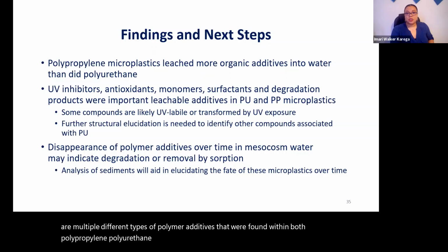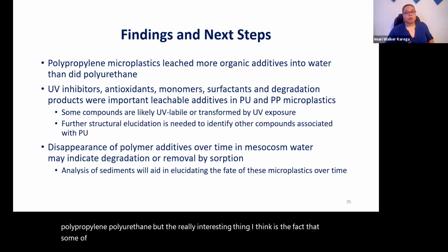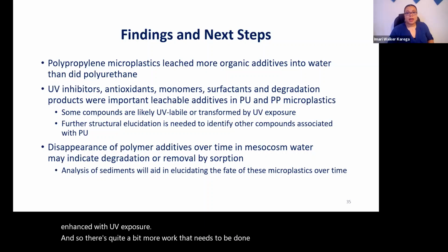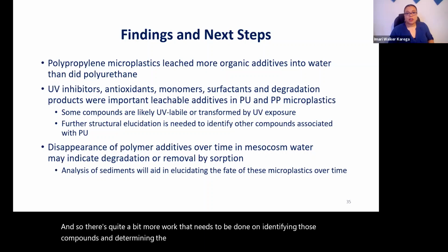The really interesting thing, I think, is that some of them don't show up without UV exposure, or are enhanced with UV exposure. So there's quite a bit more work to be done identifying those compounds and determining the mechanism of their appearance in the water.